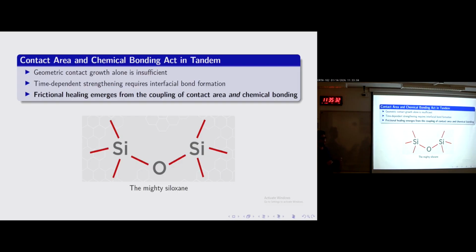And the interpretation here is that we're lacking this inherent frictional resistance from the chemical bonds. And really the contact area works together with the chemical bonds. I mean, contact area alone is just nothing without any chemical mechanism that actually makes use of this contact area. So frictional healing emerges from the coupling of both contact area and chemical bonding. And this is again the siloxane bonds that I'm talking about: silicon through oxygen to another silicon across the interface. Think of an interface around here.